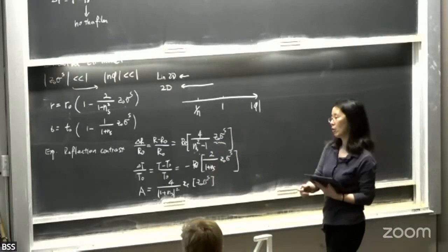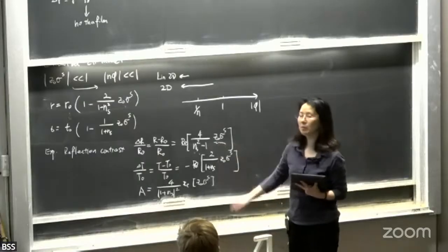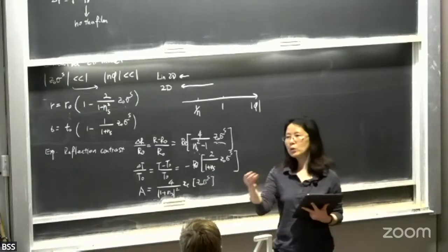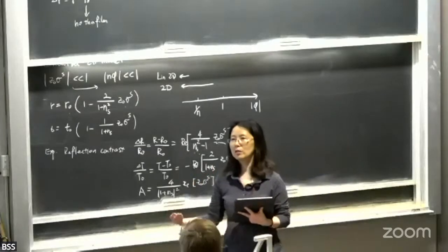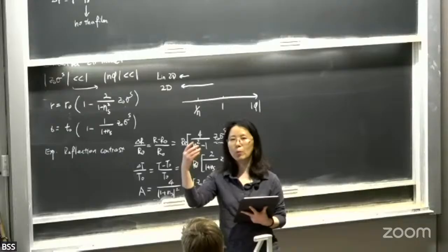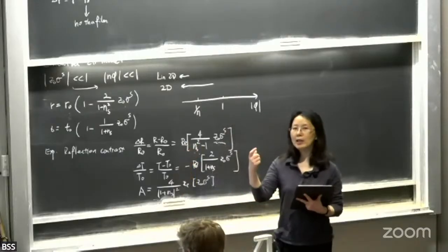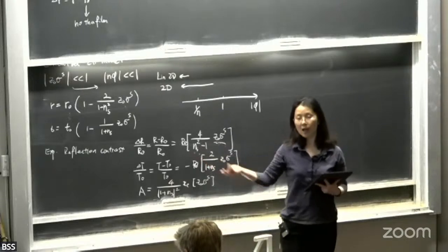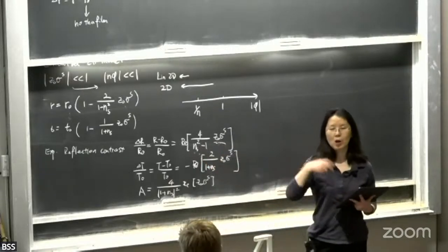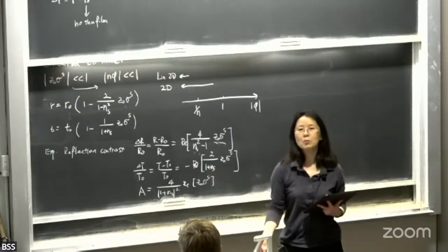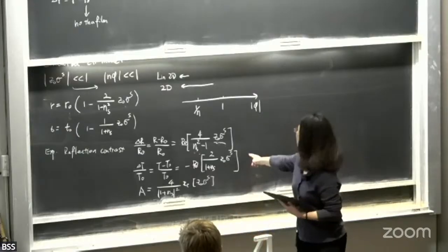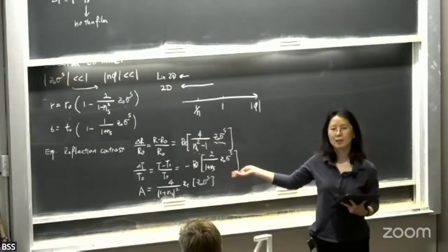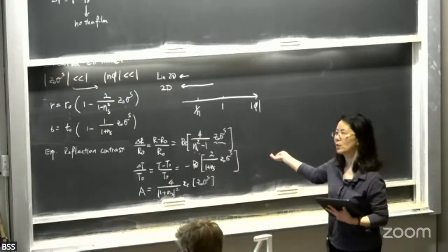So if you model your material with some function and the built-in Kramers-Kronig requirement for real part, imaginary part, and then fit your experimental result using this, and then you iterate, modify your input for the conductivity, then after many times, you may get what this is.